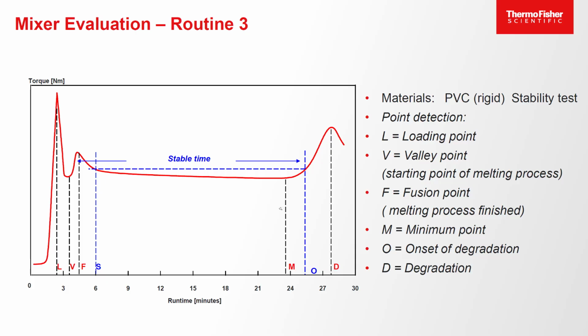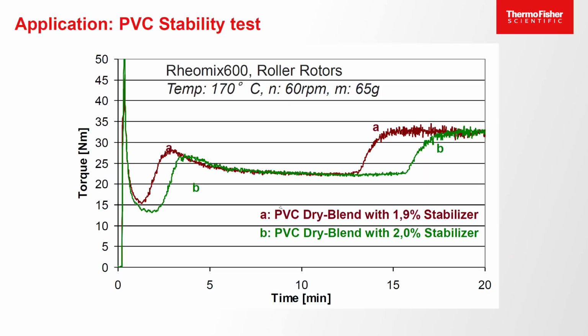Therefore, also the stability test is very common. Now let's have a look how sensitive the test is to check for this stability. Here we see now an overlay of two mixer tests. Both compounds are exactly the same. The only difference between these two compounds is the stabilizer content. One material has 0.1% less stabilizer, the red curve. So what we can see, if we look at the end of the curve, the higher stabilizer content results in a longer stability of our compound. Well, we expected that. The other thing we can see, the viscosity of my compound is not affected by this change of formulation because the curves are here exactly the same.